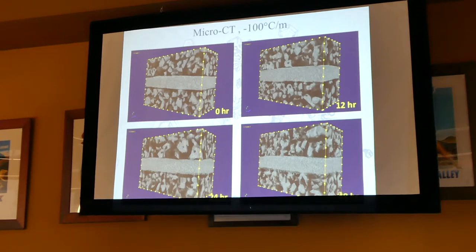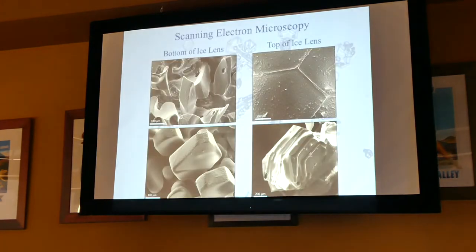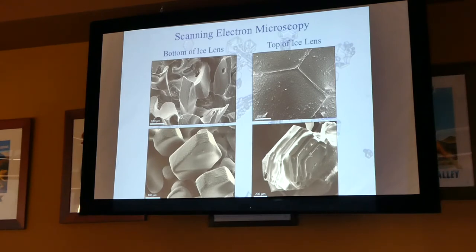The question I had was, how smooth is the top surface of this ice lens? Because the idea is that it remains smooth and it's a nice sliding surface. So I looked at these samples with a scanning electron microscope. And this is what the new ice crystal growth looked like below the ice lens, while the top of the ice lens did remain smooth. So these are grain boundaries on just a smooth piece of ice. And then, of course, we saw the faceted snow grain as well, right above the ice. So it looks like that setup we were just talking about happens naturally, where you get maybe a bigger temperature gradient near the interface, and you get more faceting there.